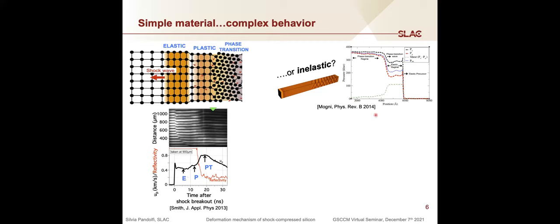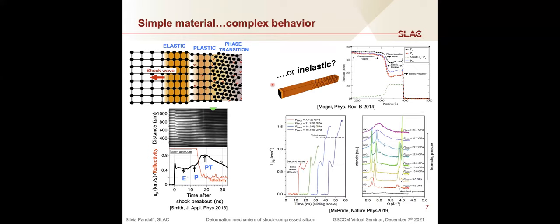What MD simulation suggested is that in silicon, it might be the phase transition itself to be the shear release mechanism. So it could happen that silicon could undergo an elastic deformation followed by the phase transition without any intermediate plastic deformation. And these MD predictions have not been confirmed experimentally yet, but have been definitely supported by some